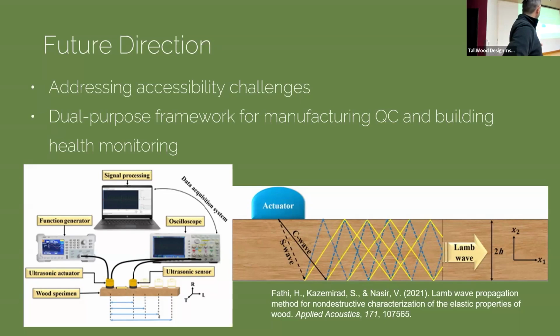So I'm also very interested to look into this form of data acquisition called pitch and catch. So basically all the data is going to be collected from one side of the panel. Is it possible that we practice that for both identifying the manufacturing defects and for the damages made during the panels' in-service condition? And in that case, basically the wave we send and receive has a more complex nature because as it travels, it's going to be decomposed into compression and shear wave components.